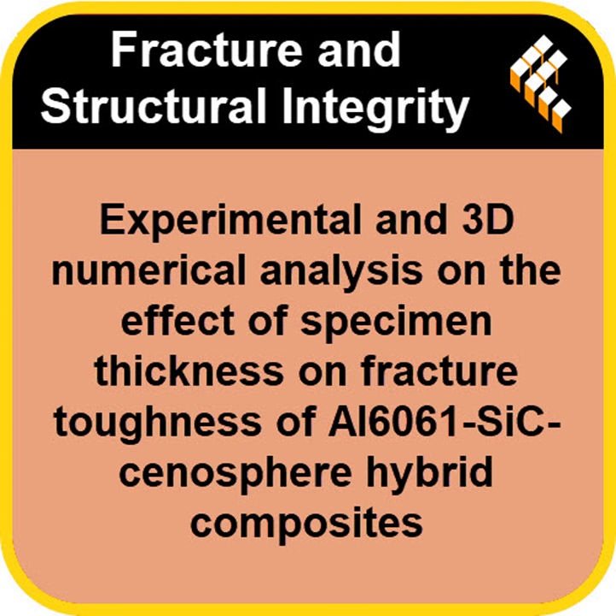Got it. And the 9 wt% sample, the one that performed poorly, that just failed because of those internal flaws, the clumping we talked about. Precisely. Those large particle agglomerates acted like big pre-existing defects. As soon as you put load on it, they initiated multiple cracks almost instantly. It's a textbook example, really, of how internal manufacturing flaws can completely compromise what looks like an excellent material composition on paper. It's really impressive, though, that they didn't just rely on physical testing. They backed it up with computational analysis, too.